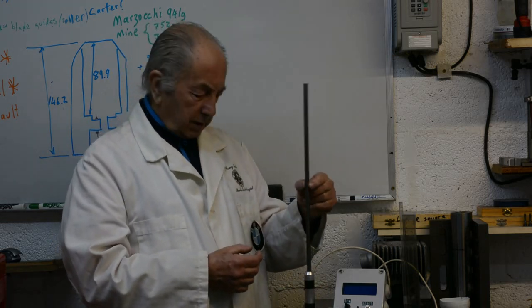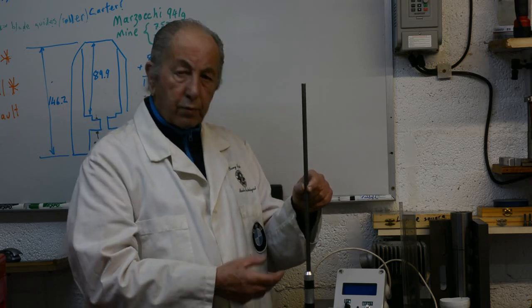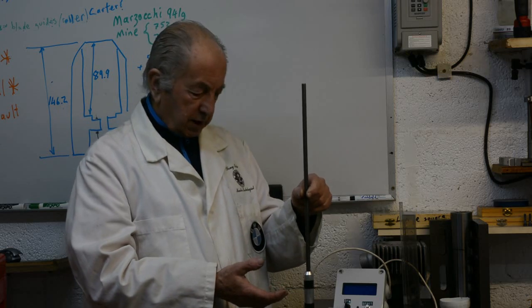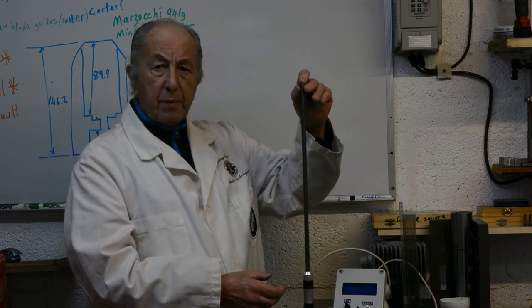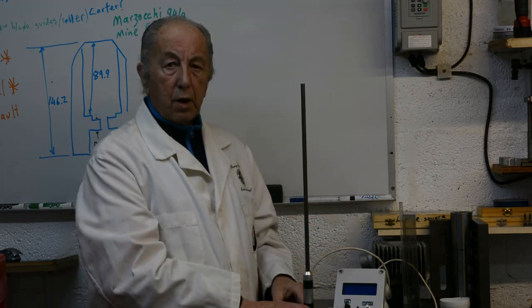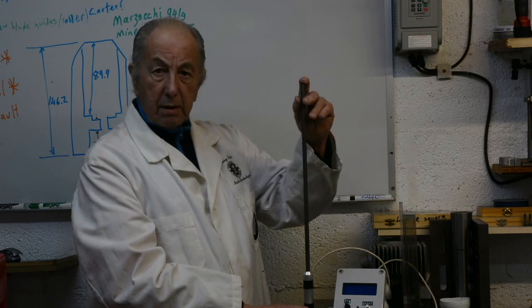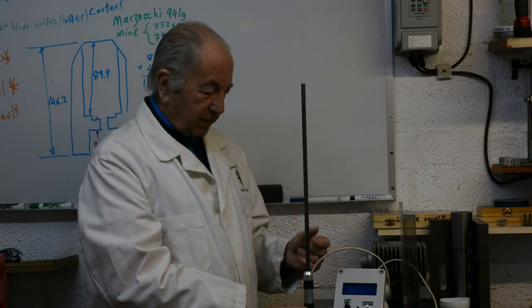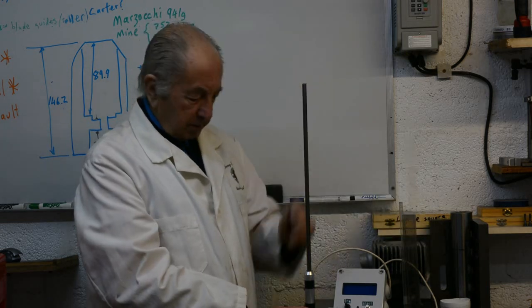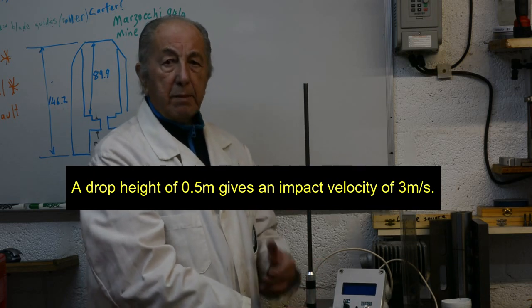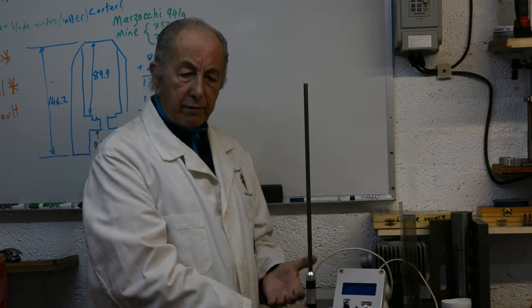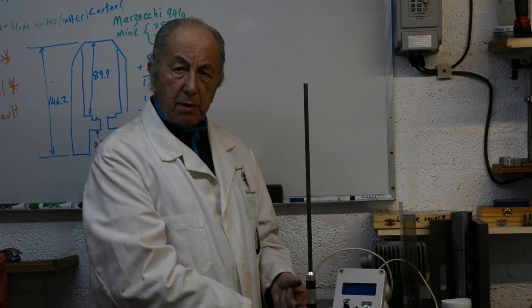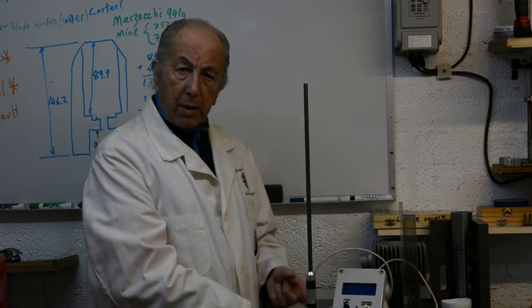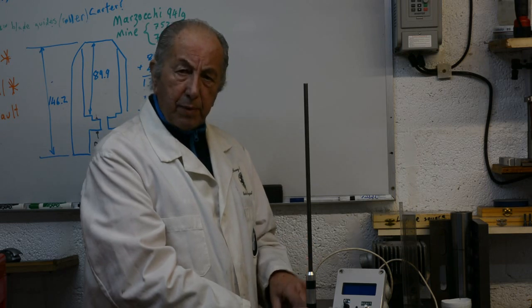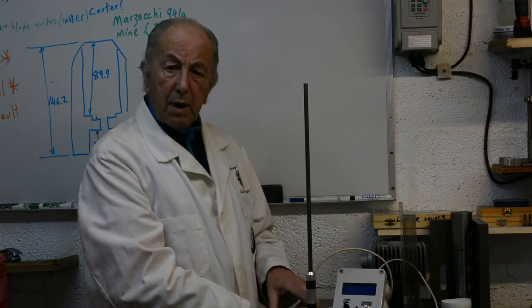Because if you drop this from half height, it will impact a bit slower, the rebound will be a bit slower, but the ratio will be very much the same. So the hardness we measure will be very much the same. The 1/2 meter for me was convenient for several reasons. One is I had a piece of steel tube that was 1/2 meter long. That's a pretty good reason. The other one was dropping it from 1/2 meter had the same velocity on impact as the Leeb. This meant that although I was using a ball dropped by gravity and the Leeb system was using a more complex impactor powered by a spring, the velocity of our impactors at the surface of the material we're measuring was in the same region.